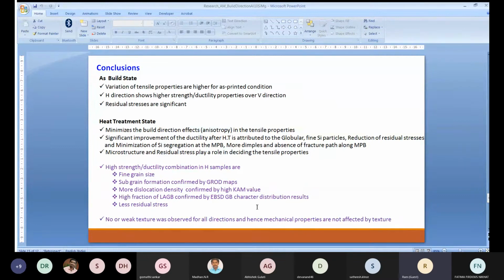The reason for the improvement in ductility is the globular and fine silicon particles, the reduced residual stresses, and the minimization of silicon segregation at the melt pool boundary by combining them and making the silicon particles globular, along with the observation of more dimples and absence of fracture along the melt pool boundary. These are the reasons for the improvement in ductility. And what we understood from this research is that surface roughness and defects have not played a key role in deciding the tensile property, whereas the microstructure and residual stresses are very important in deciding it. And there is a good combination of strength and ductility in the horizontal direction.